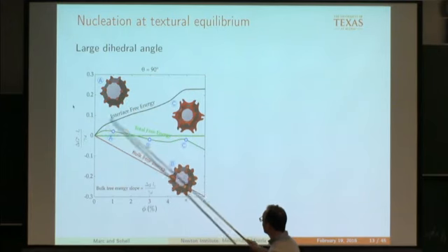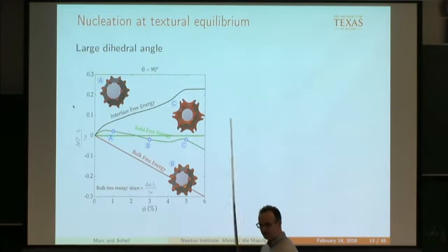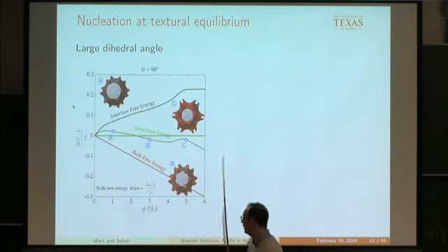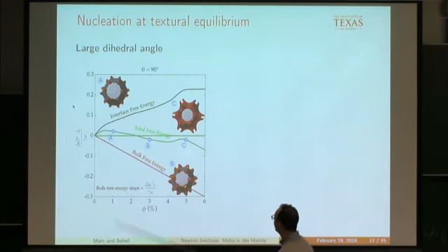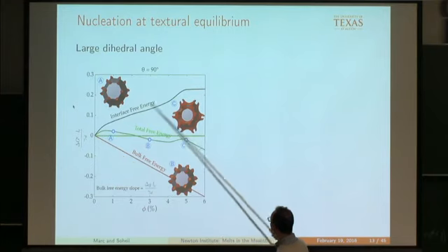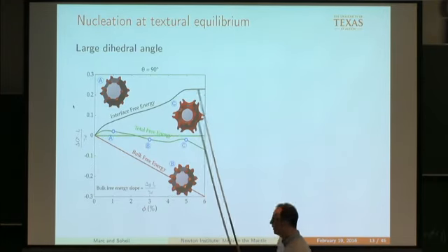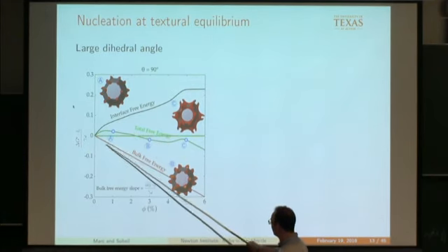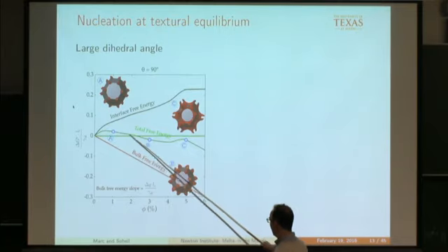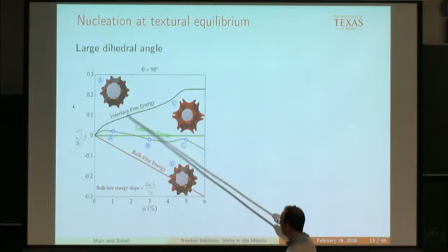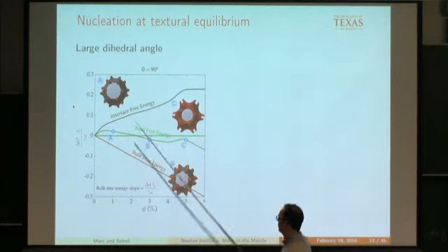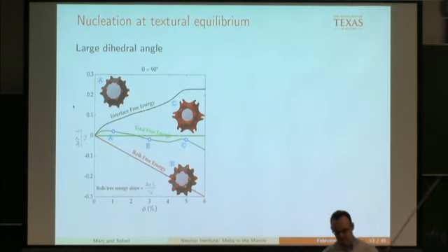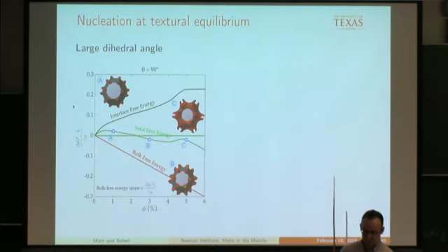And from the computations, of course, we know what the interfaces are that we've created, and what the interfaces are that we've destroyed, and we can do the sum. You see the total interfacial energy contribution is positive, very similar to the classic case. Then if you add those two together, you first get a maximum, and then it decreases, and so maybe there would be a critical porosity here, just like the classical case. Nucleating at the triple junctions. Yes.